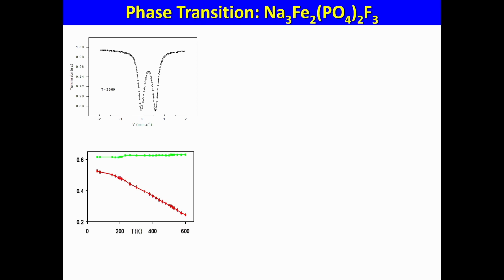So now we have done a series of spectra versus temperature because they were suspecting the presence of a phase transition. And of course, when you look not carefully, you will see that it is in the isomer shift. The isomer shift is increasing when the temperature is decreasing. Okay, right. Here you can see the evolution of the quadrupole splitting.